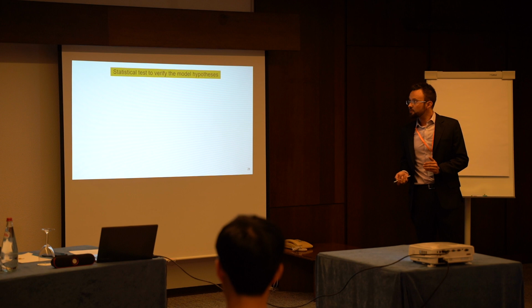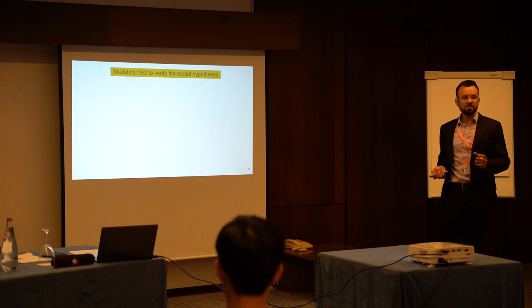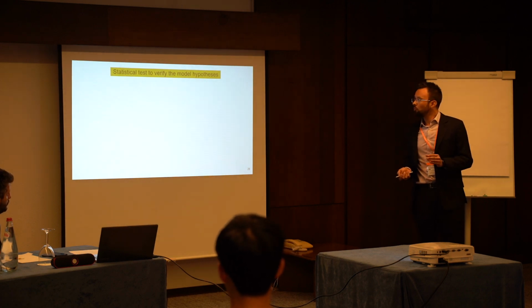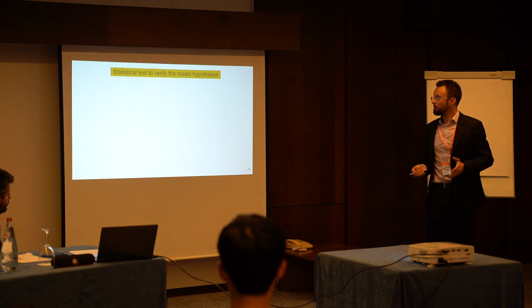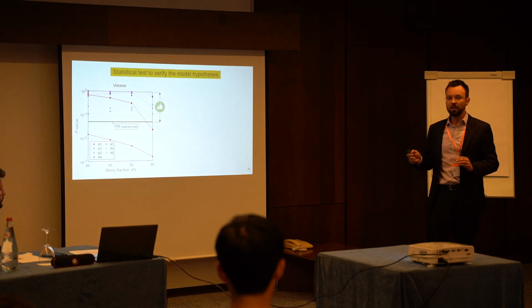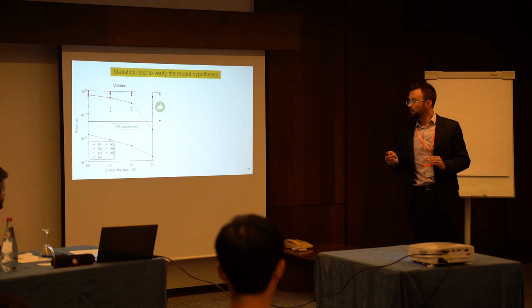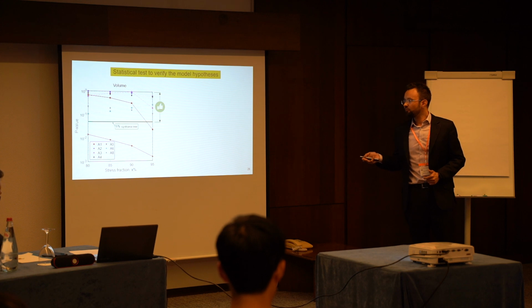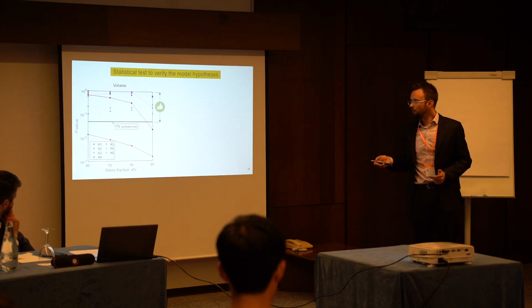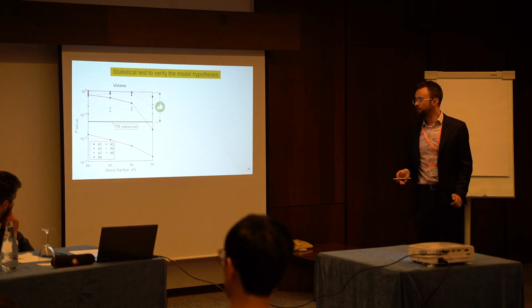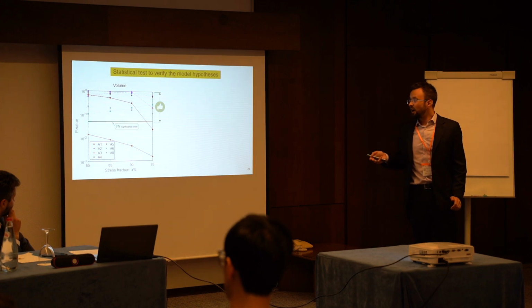And now the next step, using these values, volumes and surface, we check if our model is in agreement with our data. What is important here is that we test based on a statistical test. What is important is the acceptance ratio that is above the 5% significance level, and almost all series are above 5%, except A5 and A1 with 95% in the case of volume.